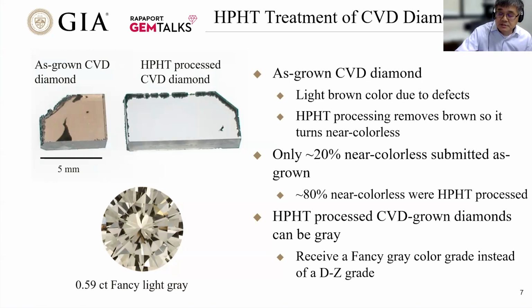So again, just what we mentioned, as-grown CVD diamond could have a decent amount of brown color, and HPHT treatment could remove the brown color, turning them colorless or near colorless. In the trade, in GIA, most of the CVD diamonds we test in our labs are HPHT treated, about 80%. But there are technologies that can grow CVD diamond colorless or near colorless, and no post-growth treatment is needed. So about 20% in our lab we tested as-grown CVD diamond.